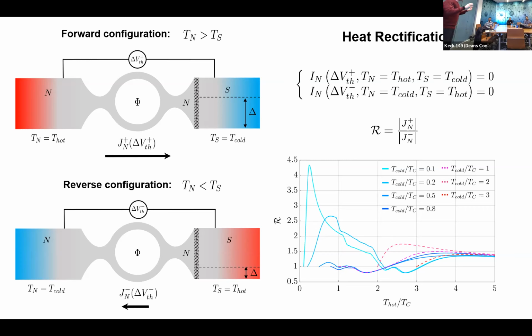It's very important. As a very final remark, I can say we have these two different regimes, the superconducting one and the normal one, right? Depending on whether the temperature is within or without the critical temperature. However, you can see that when you really exploit the superconducting nature of the superconductor, your rectification is the best one. For the normal one, instead, the only breaking of left-right symmetry is due to the thermal power and not because of the gap, so your rectification factor is small, but still finite, even for the simple system, quantum dot, or even in this particular configuration.